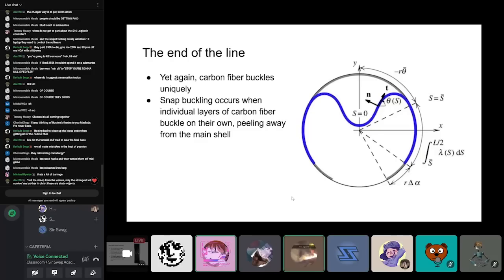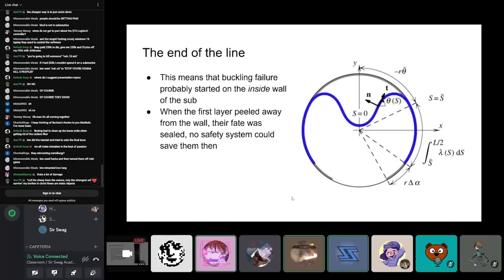And do you remember way back when I said it was half and half pre-preg wet wound with different layers? Because there were so many pores in the epoxy, that means the layers were not bonded very strongly. So they peeled away very early. And that also means that the failure started on the inside of the sub.